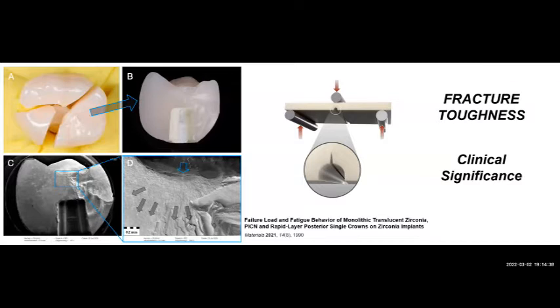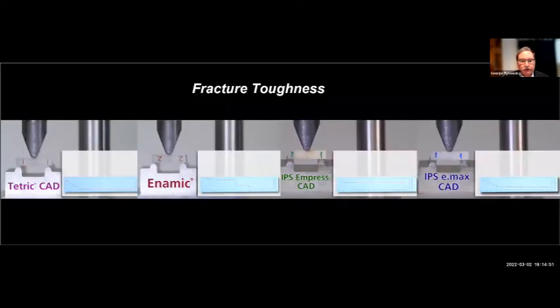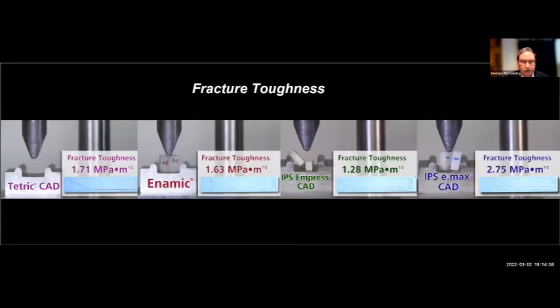Thank you. So anyway, relative to this fracture, crack propagation is what's called fracture toughness, a very relevant process where we induce a crack and we measure the resistance to the fracture of the material. Here we have again the same discs relative to the fracture properties that we're inducing on it. And you can see here going from composites to a hybrid material to Empress, which is a leucite reinforced ceramic, all the way up to the lithium disilicate materials. So we range from 2.75 all the way down to about 1.28.